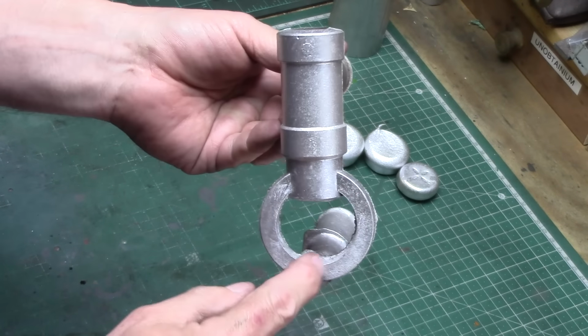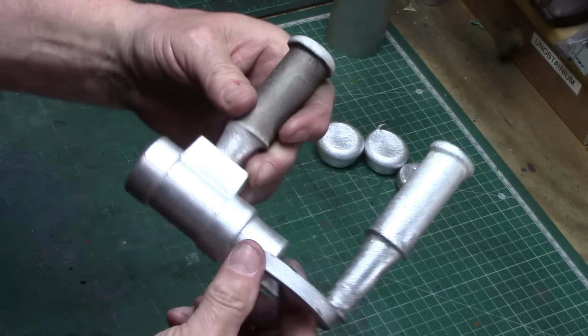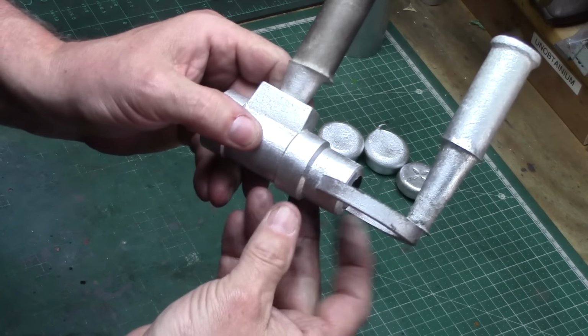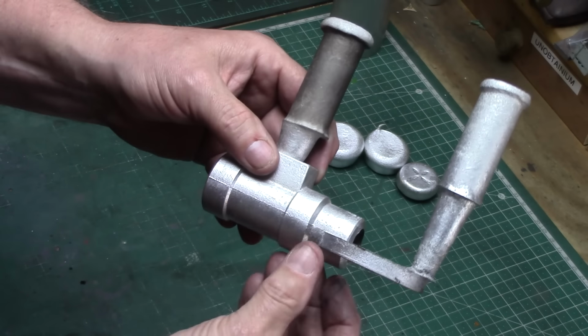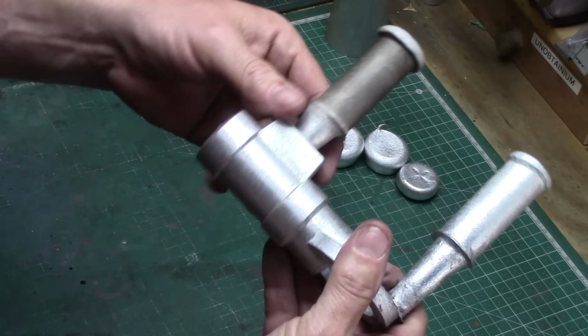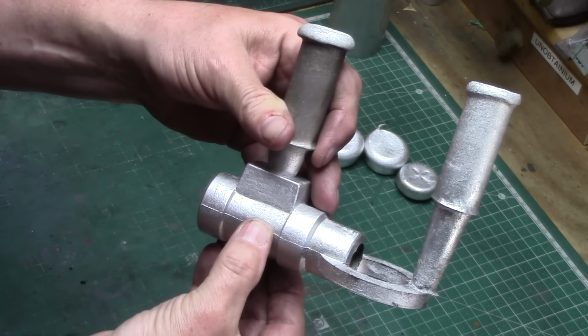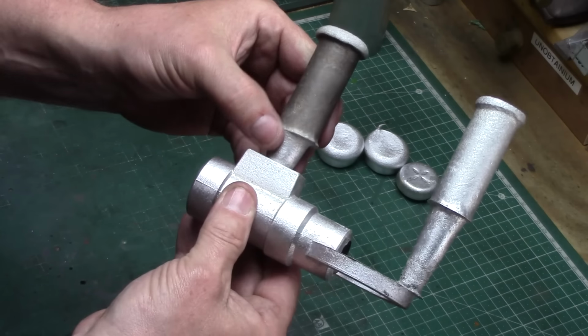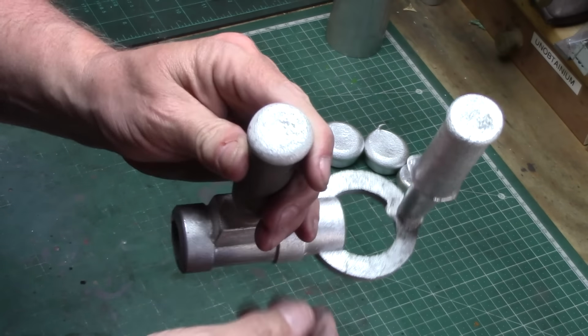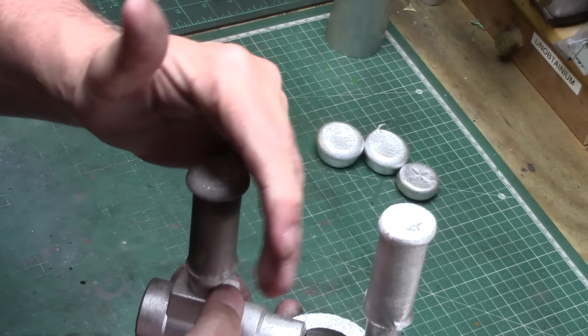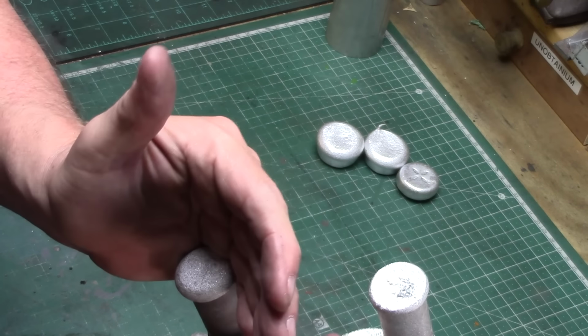The metal was poured in through the tapered sprue and into the ring-shaped gate and filled up the cavity around the core and up into the riser, or the feeder as it's also called. You can see how the top of the feeder has collapsed down as the cooling occurred. Without this, I was getting shrinkage defects on the casting itself.